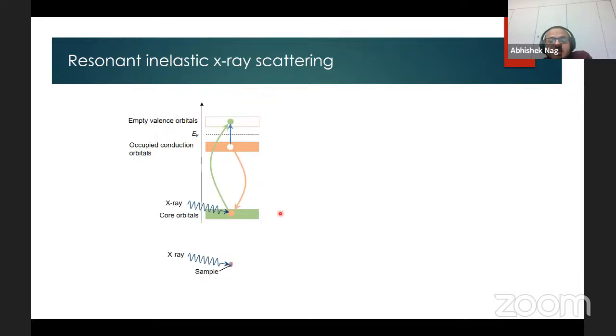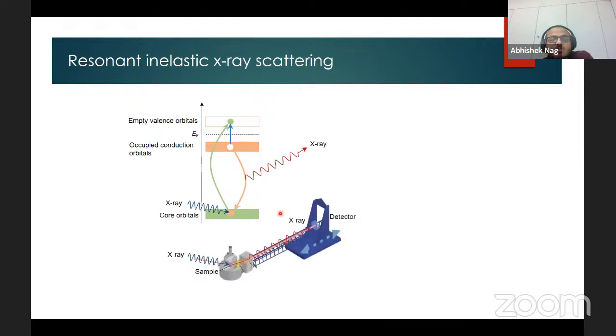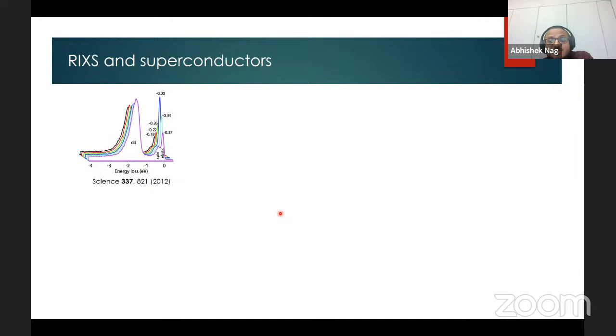If one then detects the X-ray beam that is emitted by this de-excitation process, one sees that its energy is smaller than the incident X-ray beam by an amount that corresponds to this excitation. So one can probe different element-specific excitations using this spectroscopic technique, RIXS. And RIXS has been used extensively to study superconducting materials.